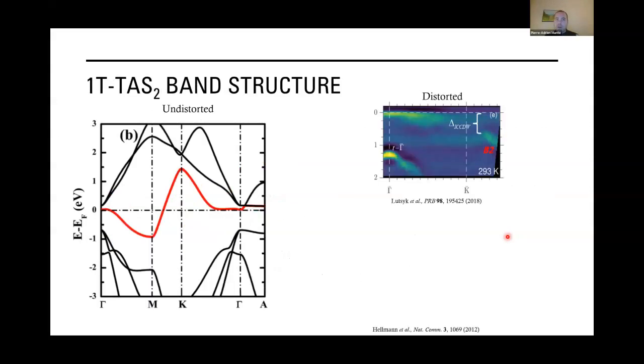Now, considering the 4 picosecond time scale, the one that seems to imply that there is a rise in the electronic temperature of the material, to understand this contribution, we need to look into a different part of the material. Indeed, there's some discommensuration that will have a specific band structure with a band that is straddling the Fermi level. But in the distorted part, in the star of David, there will be the opening of a gap due to this charge density wave between the K and the M point. So right in this region.